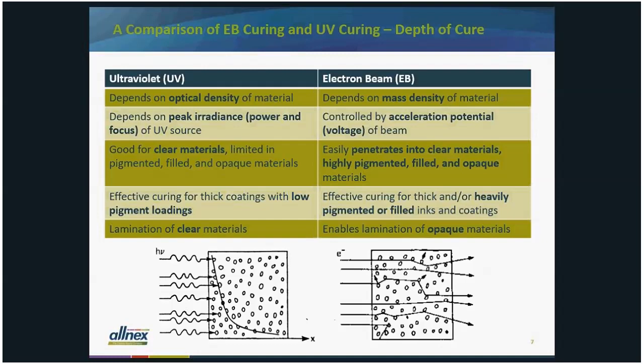And the two drawings below try to depict that. The one on the left shows that light is attenuated as it passes down through the thickness of coating, especially if there are pigments or fillers, whereas the high energy electrons will penetrate through the entire thickness of the coating, curing it all the way down to the substrate. So UV is effective for thick coatings with low pigment content. Electron beam is effective for thick or heavily pigmented filled coatings. And if you're into adhesives and you're doing laminated adhesives with UV, you can cure if those materials are clear. But electron beam can cure even if the lamination is done using opaque materials.